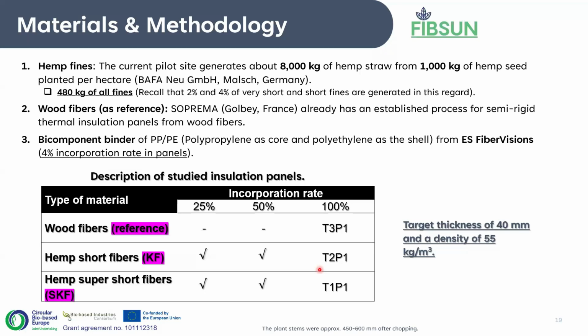So for this particular aspect, we already have a partner, SOPREMA, that is working with wood fibers in insulation products. The whole concept was to incorporate fines as a partial substitute for wood or as a total substitute. And again, we worked here with the bicomponent fiber, the PE. In this case, I will introduce some of the panels we've worked with. First, we look at the wood reference, which is the panel from 100% incorporation of wood. Of course, this is important so we can compare our results.